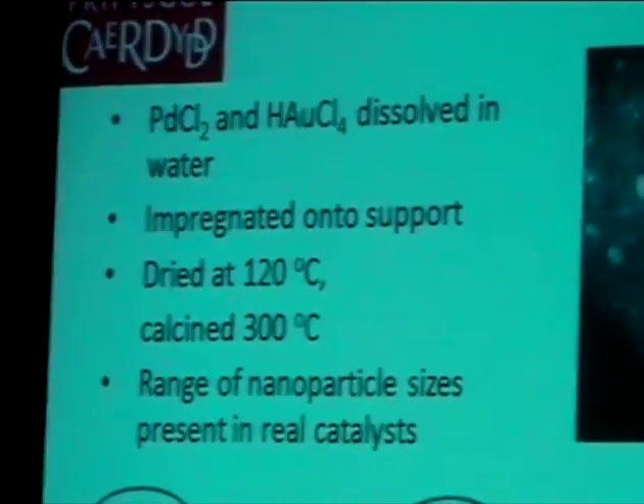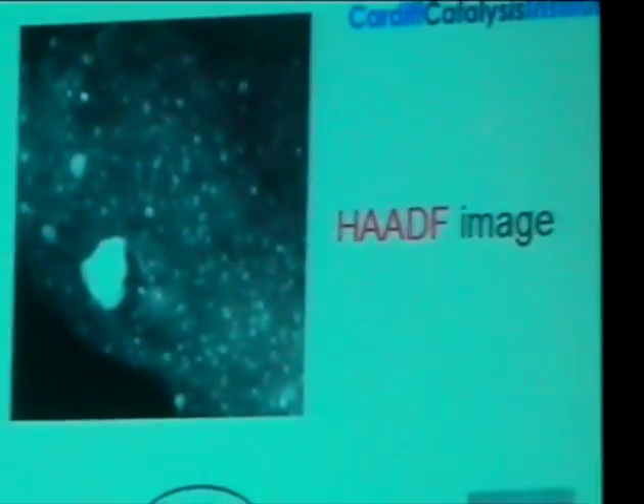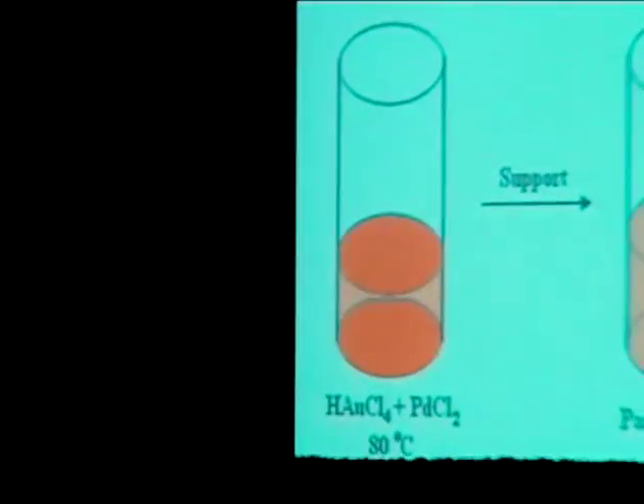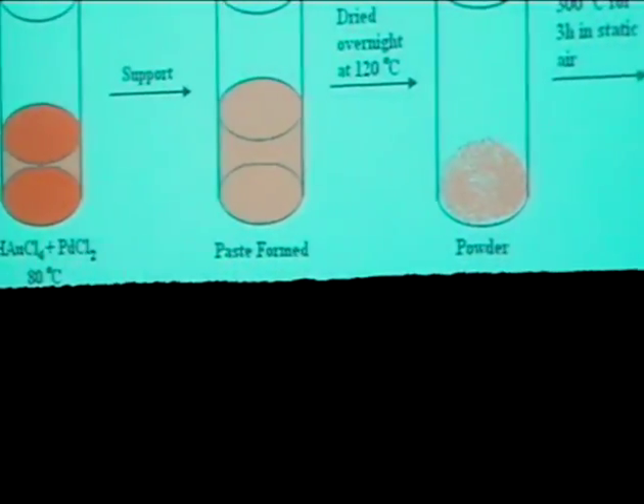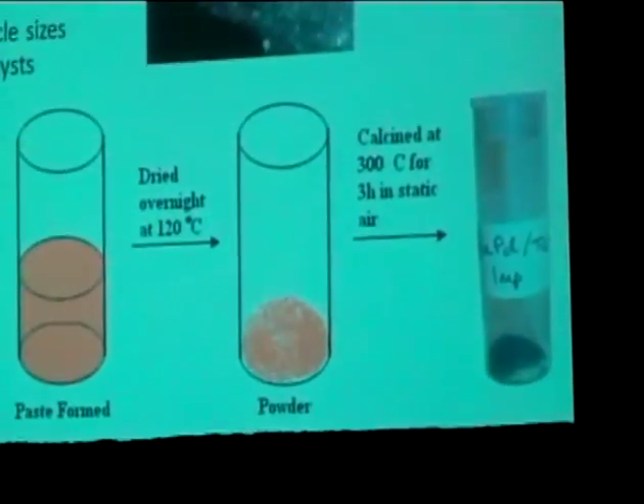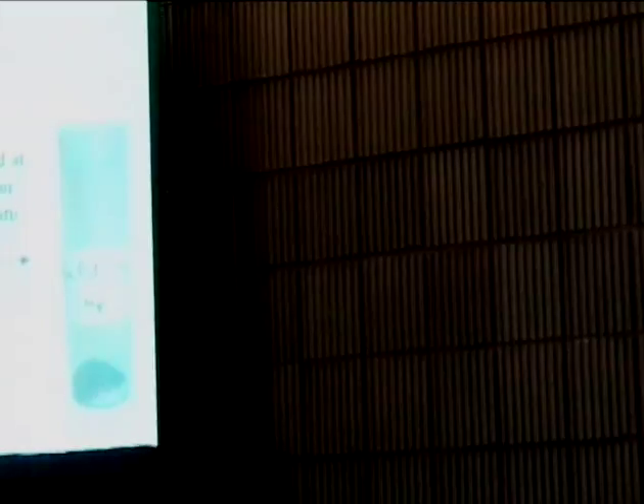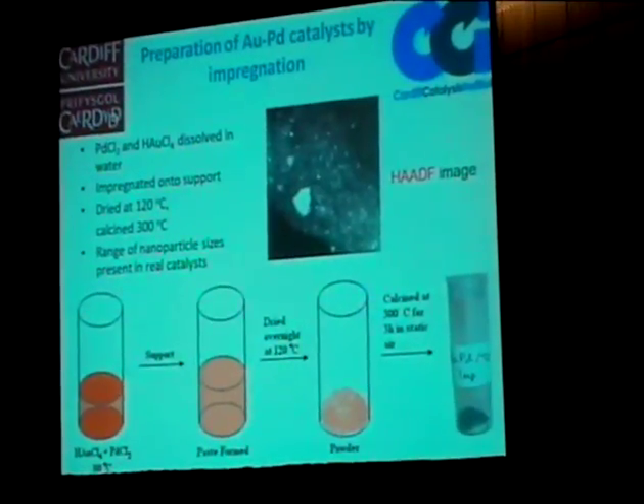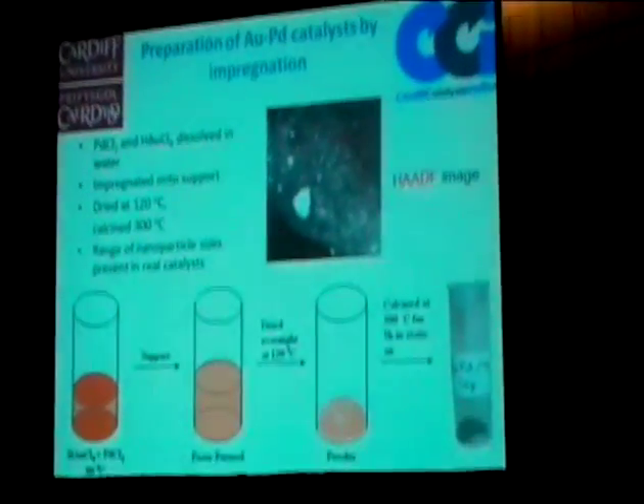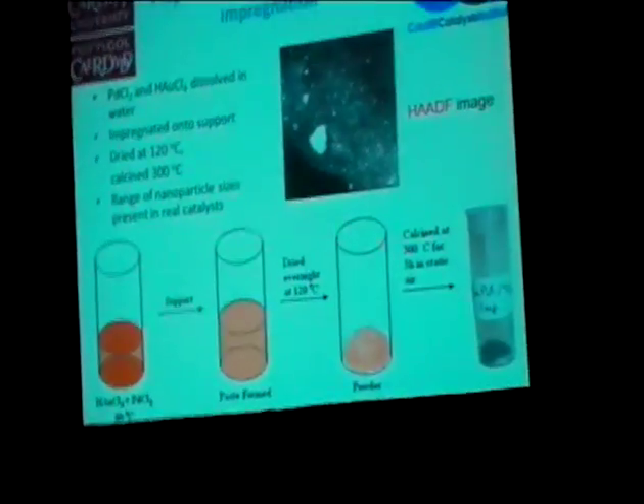One such system that has been extensively studied is the gold palladium catalyst. One of the simplest ways of preparing a gold palladium catalyst is by a standard wet impregnation method. So you take the palladium chloride precursor with the gold precursor, dissolve in water, heat it up slightly to 80 degrees to ensure the palladium dissolves, and add your support, typically titania or silica or carbon. You then dry off the support to form a paste by evaporating water out of the preparation, and then you calcine at high temperature in an oxygen environment.